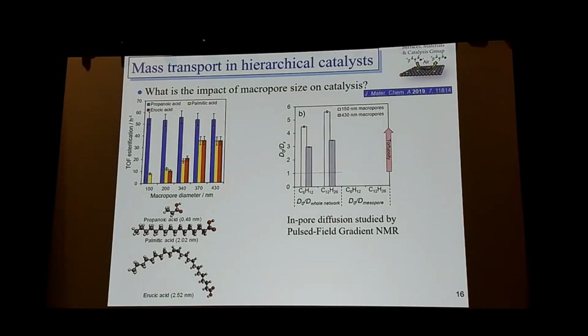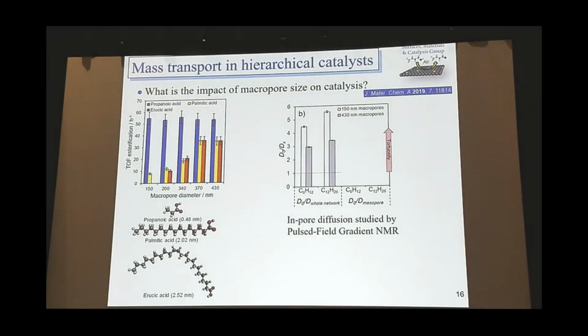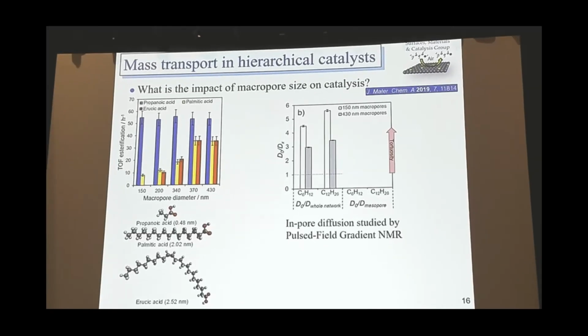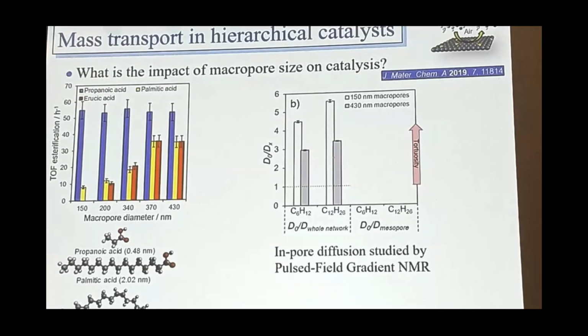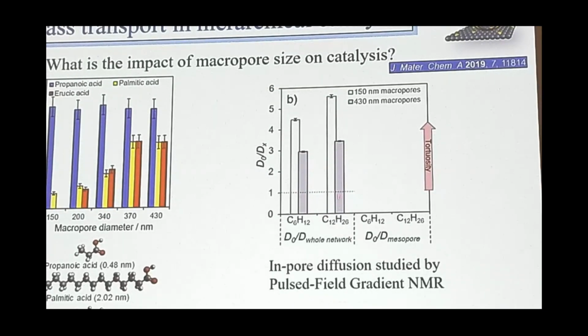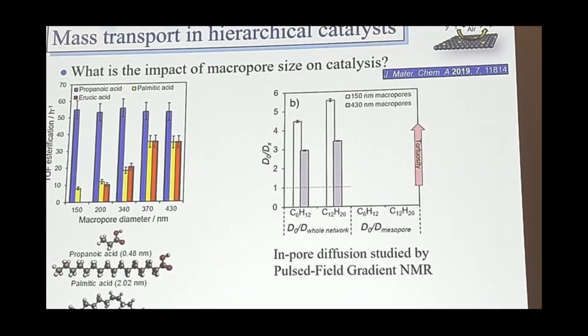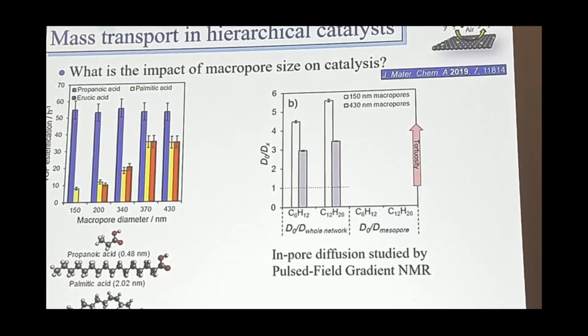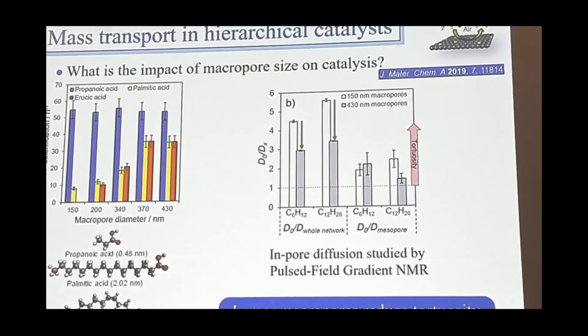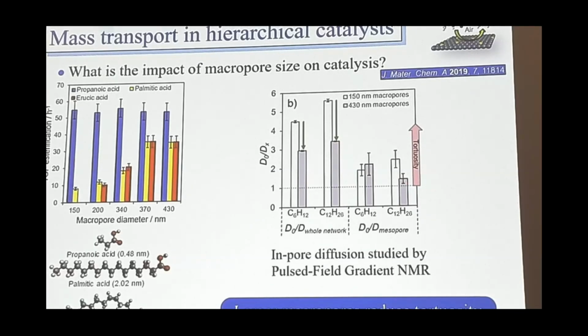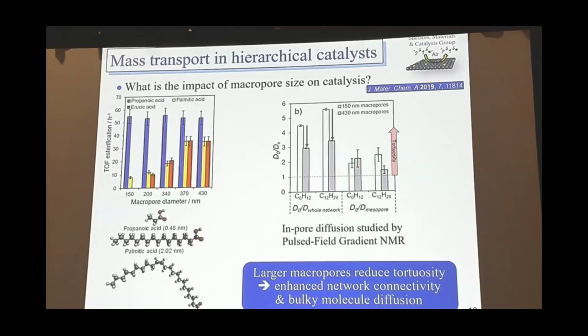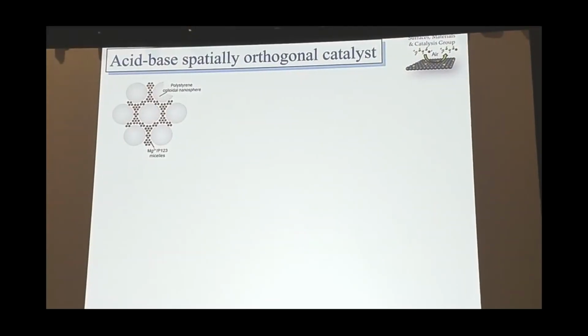And we've used pulse field gradient NMR to actually demonstrate the impact of macroporosity on the tortuosity of the molecule moving through the pores. So here what we looked at is two different pore networks and the diffusion of C6 and C12 molecules. If there's no tortuosity, then these bars should all be one. And you can see that they're significantly higher than that, suggesting that there is some mass transport limitation, but that tortuosity gets less as you go to larger pore materials. And if you look at the diffusion through the mesopore, diffusion doesn't change at all. So the molecules move at the same speed through the mesopores, but the impact of the macropore is really getting the molecules out of the structure itself. Okay, so we can actually demonstrate now that we do have this beneficial effect.